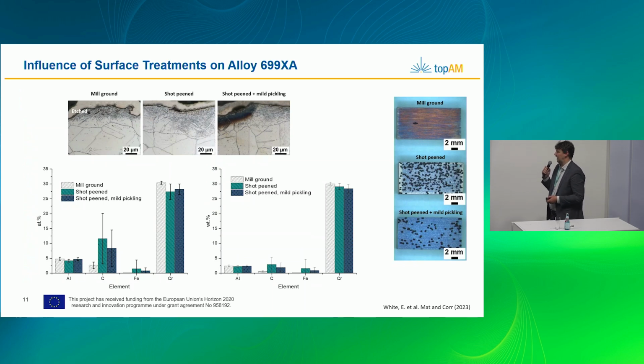What we found, on the other hand, is significant amounts of iron. And iron on the surface from the shot peening process, basically, this was an industrial shot peening process where lots of materials go through. So of course, this was a nickel-based alloy that is basically iron-free. But obviously in the shot peening, before that there were some austenitic steels, for example, some other steels. And the residues of those can be found on the surface. And iron is very active and very catalytically active with this carbon deposition. So the post-processing basically decided if this material is resistant in the application or not.